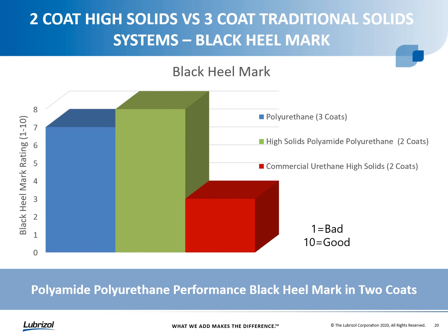And we can see here when we compare the 3 different systems that just 2 coats of the high solids polyamide polyurethane gave the highest black heel mark resistance, coming in at an 8 out of 10, followed by the traditional polyurethane system, in this case a 3-coat system, coming in at a 7. So again, being able to deliver higher performance in 2 coats than the 3-coat system, and then compared against the commercial high solids urethane 2 coats, significantly higher performance, as the commercial product came in at a 3, with significantly more marking that remained on the surface.